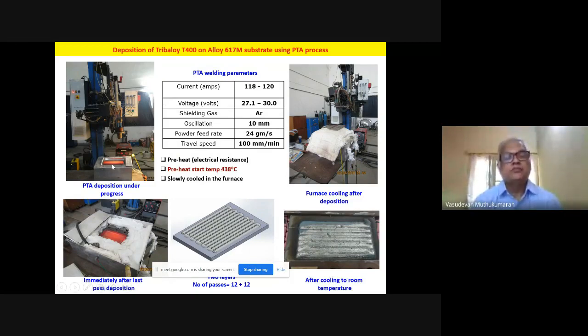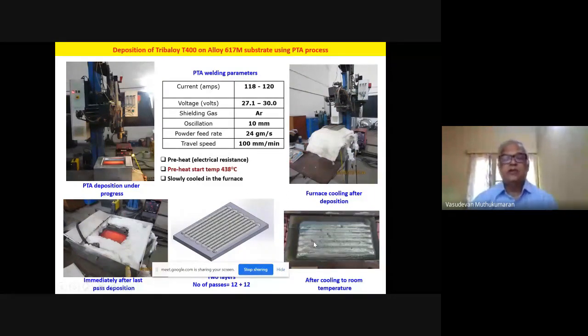Here overlaying is being done. Here the material is Tribaloy T400, deposited on alloy 617. These are the parameters used. It needs to be preheated by electrical resistance and then slowly cooled in the furnace. You can see the furnace cooling after deposition. You can see the deposited substrate, and this is the hot face coating. And we could successfully demonstrate that.